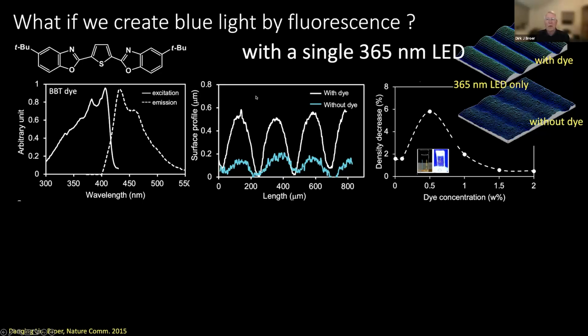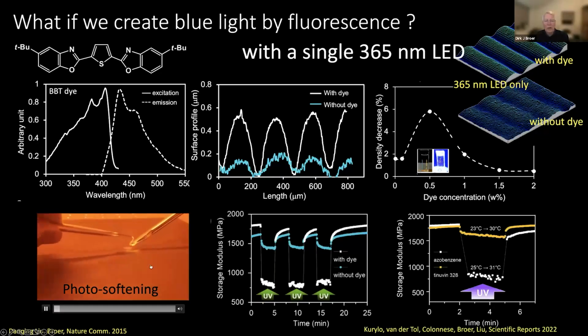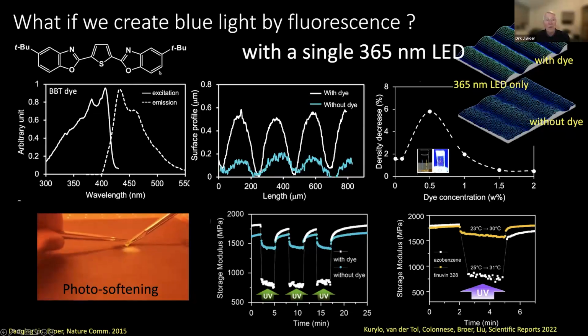And not only is the deformation enhanced, also the photosoftening effect is enhanced by just adding a little bit of this fluorescent dye. So in this case, just by exposing to the UV light in the presence of the dye, you see that the modulus decreases from, in this case, around 1500 megapascal to a few hundred megapascal, which is shown here and basically also shown here. In this case, we compare it again with a material which is absorbing at the same wavelength as azobenzene, only seeing small effects. And in the case of our actuating system, you see the large reduction in the modulus.